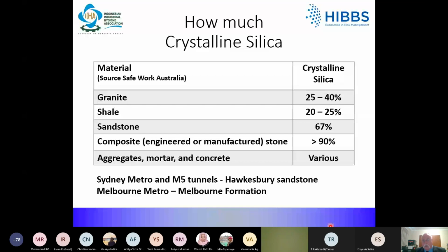And then you've got engineered stones and other composites that contain greater than 90% crystalline silica and a high percentage of cristobalite as well. And then concretes, aggregates, and mortars. It's varying depending on the amount of sand content present. We'll talk a little bit about the Sydney Metro and M5 tunnels. Sydney is essentially underlain by Hawkesbury sandstone that contains a very high percentage of crystalline silica, and the tunnel boring machines have been cutting through this silica for the last 4 years, I think it is.